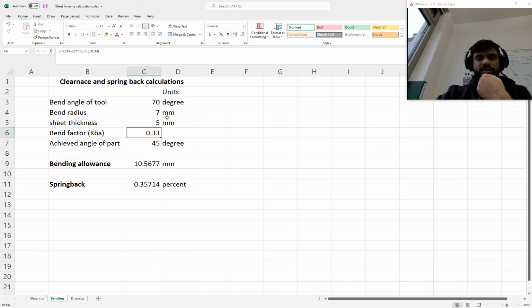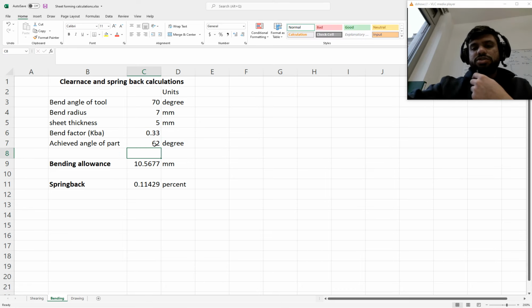Here I have applied a conditional, so the bending factor is automatically chosen based on the values which we give here, and then the achieved angle of the part, let's say it was 70 and then we achieved was 62 degrees. So we see that the bending allowance should be 10.56 millimeters, and the spring back in the sheet, depending on the achieved part angle here, is around 11%.